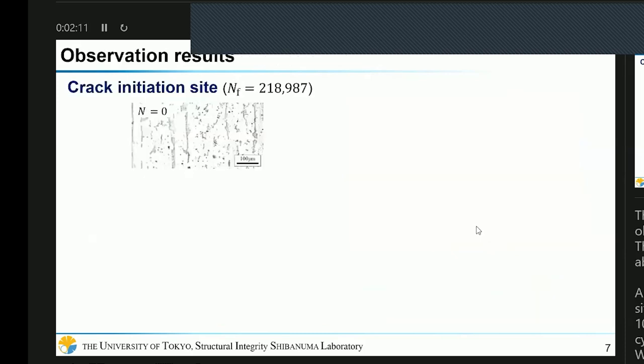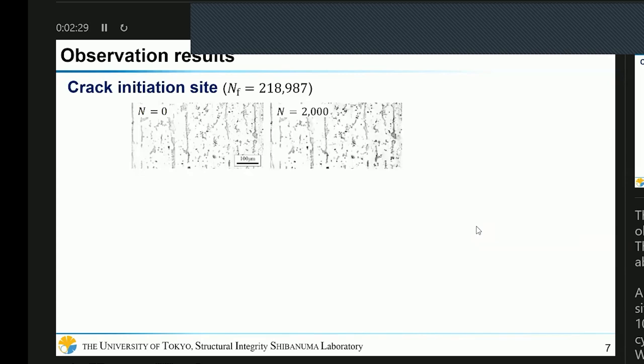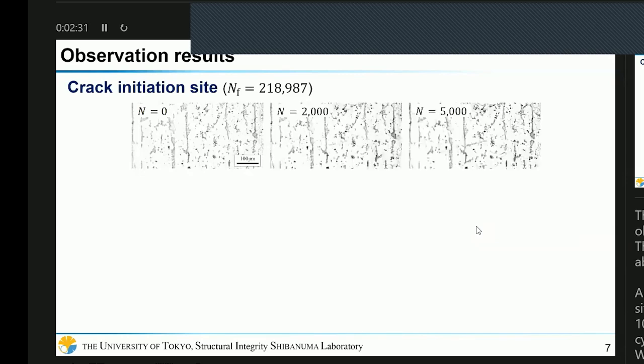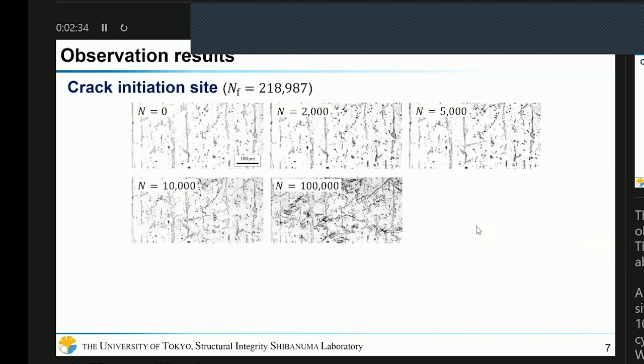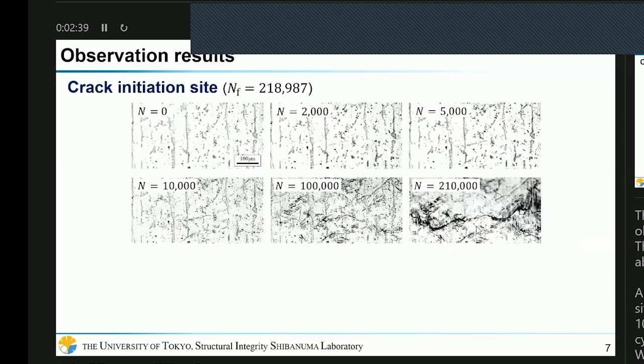And this slide shows the observation results. The final number of cycles to failure was about 220,000 cycles. It's a typical ordinary high cycle fatigue condition. So this photo is a crack initiation site. 0 cycle, 2,000 cycles, 5,000 cycles, 10,000 cycles, 100,000 cycles, and 210,000 cycles. It's just before failure. So we can see crack initiation and growth from here.